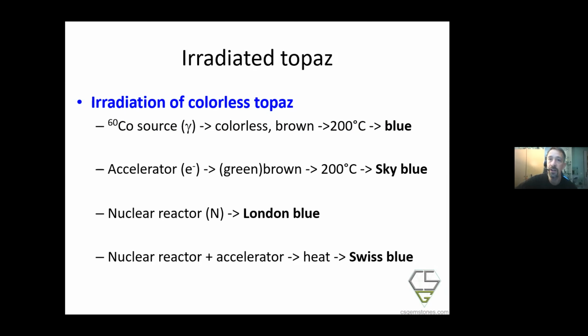UV radiation, for example, is one of the enemies of the brown color. And the other thing is temperature. So you turn them to 200 degrees, they turn blue. If you heat them up to higher temperatures, they might turn colorless again. However, the difference between these two temperatures, where you turn them blue and you destroy the blue again, is so high that the blue color is considered to be stable. So whenever you cut it, you put it into jewelry, you wear it, this color is stable and does not fade with sunlight.